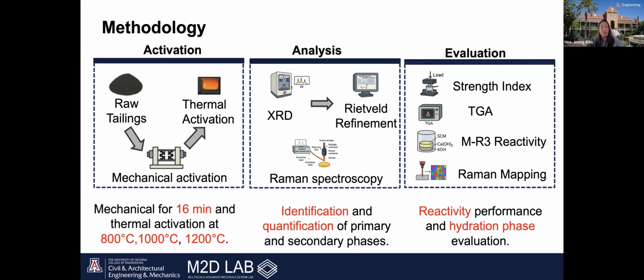So all activated samples were analyzed using XRD and Raman spectroscopy, and we performed quantitative phase analysis with Rietveld refinement, and each refinement showed a goodness of fit below 1.5, which means the result is very reliable. And since our goal is to use these tailings in cementitious materials, we tested their reactivity using compressive strength tests, TG/DTA for bound water analysis, and Raman spectroscopy. And finally, Raman mapping was used to identify the reaction products and confirm how reactive the material became.